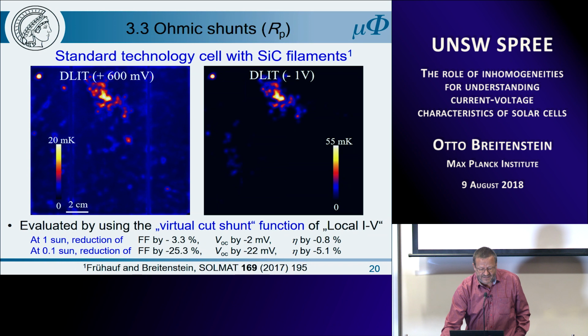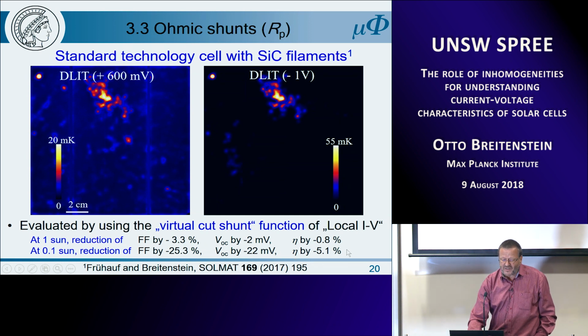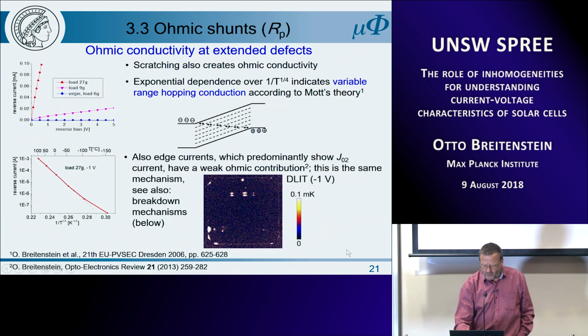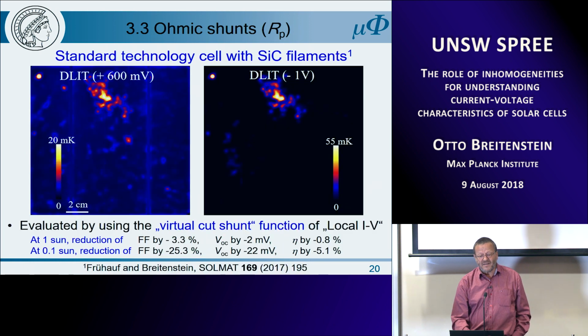And then at one sun, the reduction of the fill factor is 3.3%. Absolutely, it's quite something. VOC only 2 millivolts. And the efficiency, at least, is influenced in this heavily shunted cell by 0.8%. But at 0.1 sun, the reduction of the fill factor is 25.3%, so really amazing. VOC by 22 millivolts and the efficiency by 5.1%. I will come to the conclusions later on, but this is much stronger. But let me remind you, this is a heavily shunted cell.